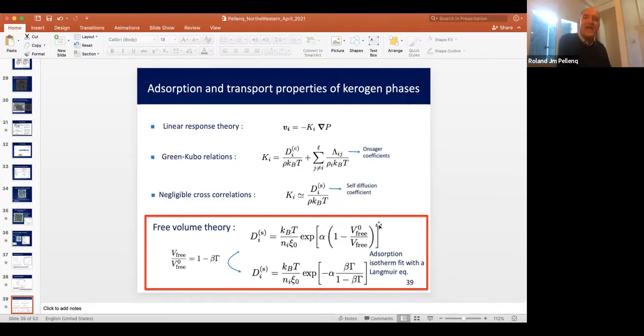This is very interesting. And not only that, following de Gennes back in the 80s, nothing to do with shale gas, he was studying the way polymers can diffuse in a melt of polymers, and he put down this free volume theory, which relates to how much free volume is left for given conditions. And when we do adsorption, the free volume is actually the amount of space free in the pore. So we can relate the free volume to the adsorption isotherm I was showing you, the amount of fluid as a function of pressure, which, because we are in nanopores, can be fitted to a Langmuir adsorption isotherm. Meaning that there's no way you can study a phase transition, a capillary phase transition, those things. The pores are way too small.